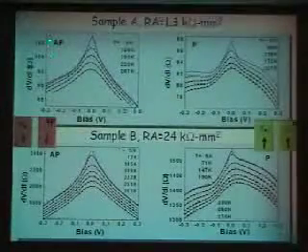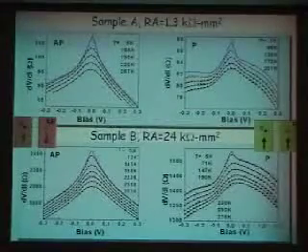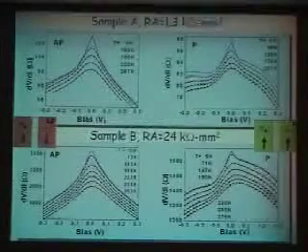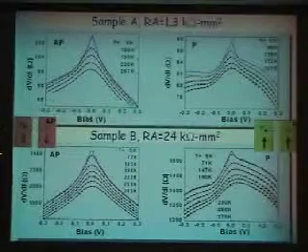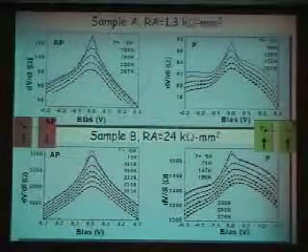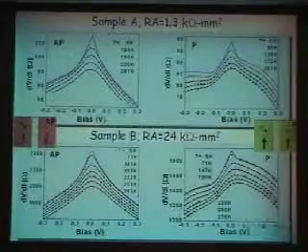So there it is. We take the zero temperature data and we convolute it with the smearing of the Fermi function. And whether you're in the parallel direction or the anti-parallel direction, it doesn't matter. The fit is excellent. And the thermal smearing has to be there. All right? There's a problem. There's a slight problem actually.